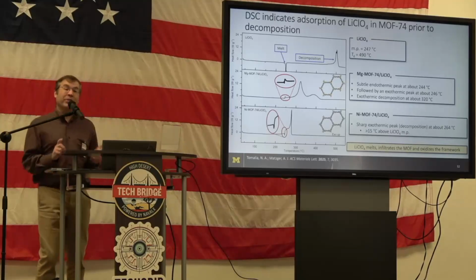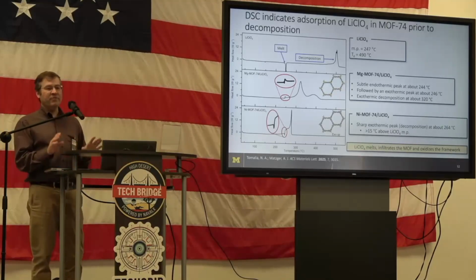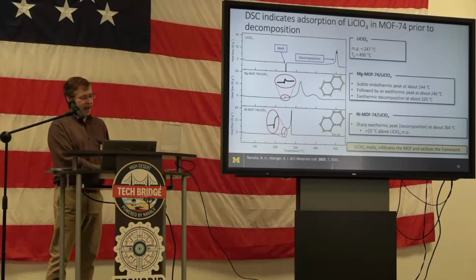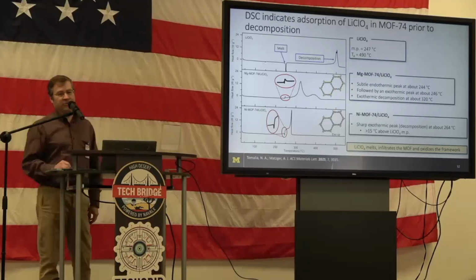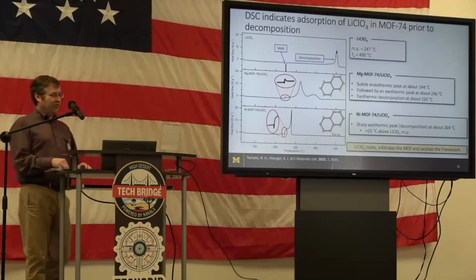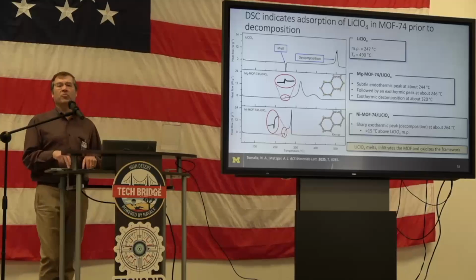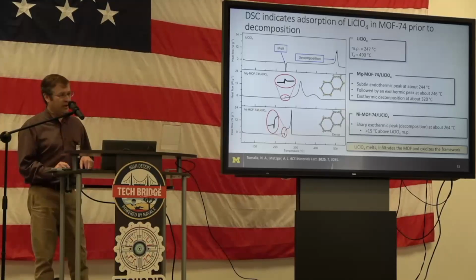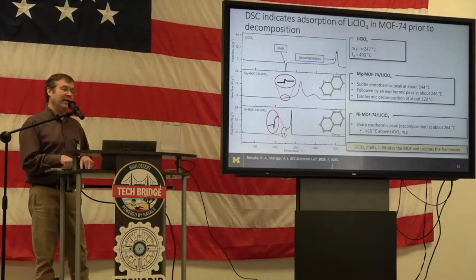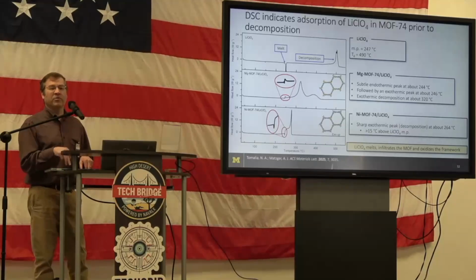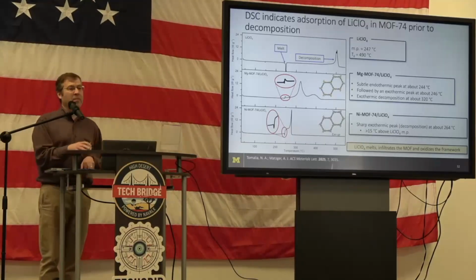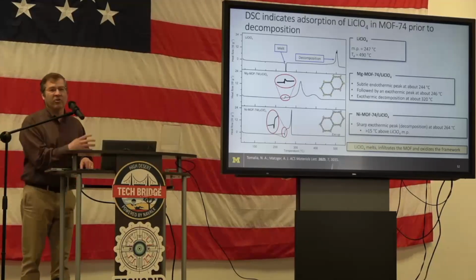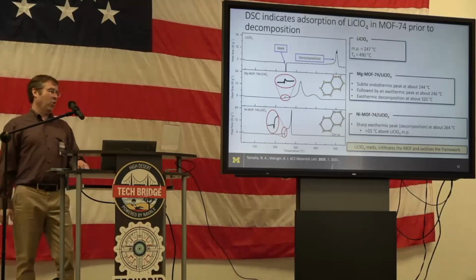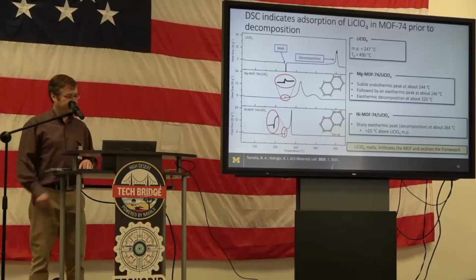Now, if we do this with the nickel compound, very different story. Now it melts and explodes. And that is because nickel is a much better catalyst for perchlorate decomposition than magnesium. So that oxygen becomes available right after the melting of the lithium perchlorate, starts oxidizing the framework, and the whole thing runs away.